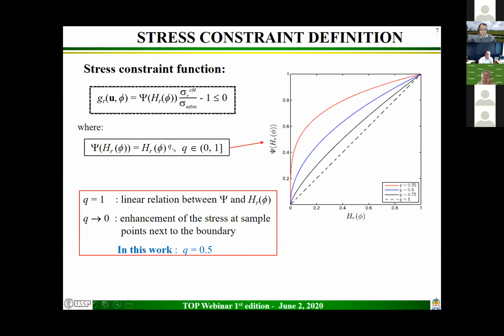So essentially, you have this exponent q here. So if q, for example, is equal to 0, this psi function will enhance the stress at sample points next to the boundary, even if the area fraction has a small amount of solid associated to the neighborhood. However, if you consider very small values of q, we may get some high oscillations in the stress constraint. So in this work, we adopt q equal to half.